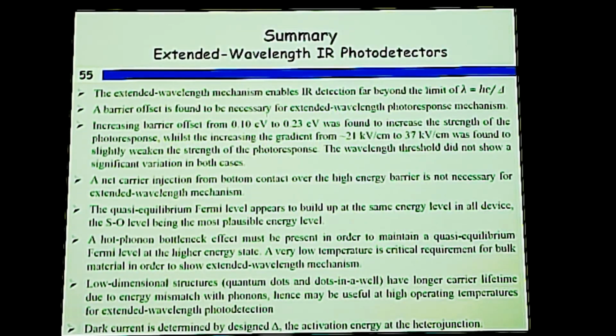So to summarize, the extended wavelength mechanism enables infrared radiation detection beyond the limit of this conventional rule. Experimentally, it was found that a barrier offset is necessary, because without the barrier offset, we didn't see any extended wavelength photoresponse. Increasing the barrier offset, we saw increasing photoresponse, but with the gradient, it didn't change much. And we observed the extended wavelength mechanism even without a net carrier injection with the bias; we observe that result at 0 volt. So that means the quasi-equilibrium Fermi level appears to be at the same level from device to device.